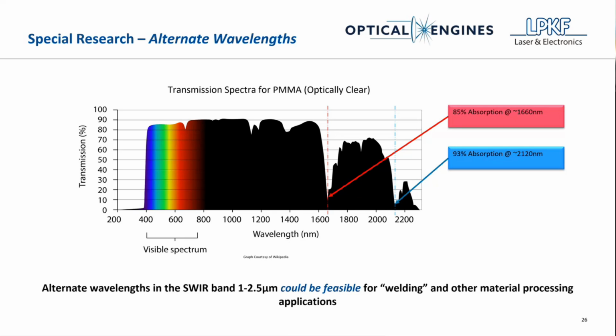In certain cases, this could be beneficial because with that transmission rate being higher, we can get a lot more energy into that plastic. But conversely, it's going to heat up a lot quicker, and we're going to have issues with thermal deformation and expansion and so on. So again, looking into this, it's new technology, potentially could work for thinner materials, films, and so on and so forth, and get a better weld.